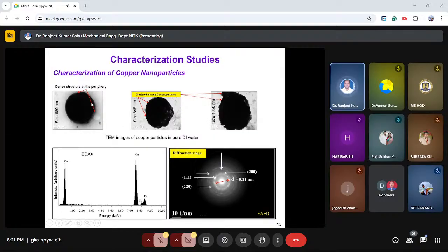Such large particles are well-defined single particles, obtained due to the agglomeration of particles at a very fine level, which results from the combination of van der Waals forces of attraction and Brownian motion during condensation and nucleation of copper metallic vapors. This image shows a submicron size copper particle with a dense structure at the periphery. This may be attributed to the collision of nucleated nanoparticles to form larger sizes.